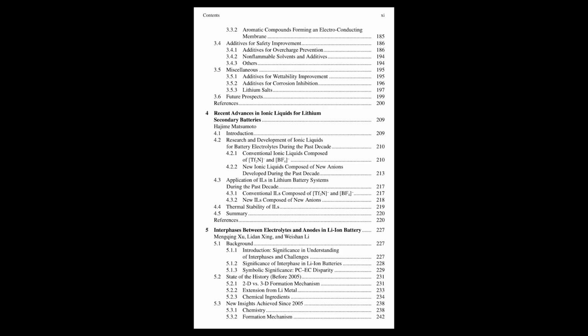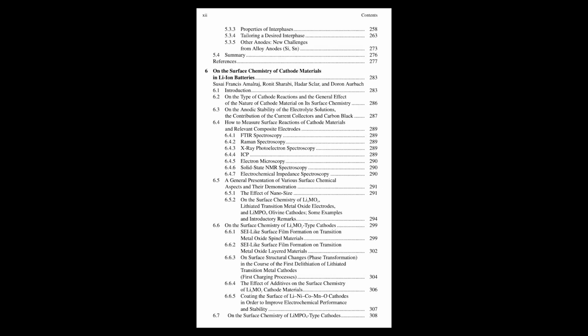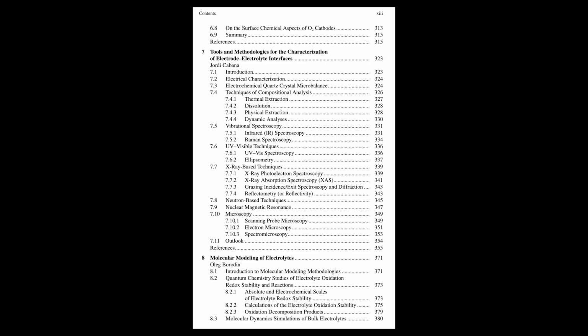Then we have the current king of the hill, lithium hexafluorophosphate, LiPF₆. What's its secret? Why is this the one? Well, LiPF₆ has proven to be the best all-around performer so far. In the non-aqueous solvents used in lithium-ion batteries, it provides electrolytes with really high conductivity. And importantly, it also reacts in a way that forms a stable protective layer on the aluminum current collector, preventing that corrosion issue we just talked about. So it solves that problem. Exactly. It's not perfect. It can be a bit sensitive to moisture, for example, but it strikes a really good balance of all the necessary properties.